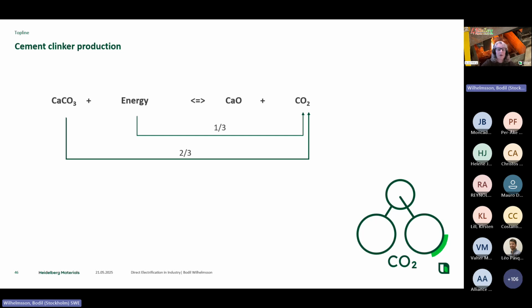And if we put some figures on it, we see that 1/3 of the CO2 emissions come from the energy, only 1/3. So the major part of the CO2 we get in cement production is from the raw material. So we have, as I said, twice the challenge. And approximately 8% of the global CO2 emitted from industry is from the cement industry. So that is a challenge we need to face.